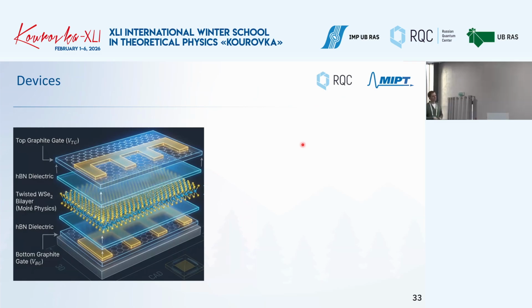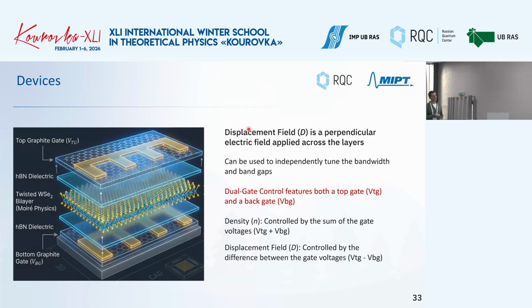While having this, you can change the so-called displacement field. It's the perpendicular electric field applied across the layers, so it can be used to independently tune the bandwidths and the gaps. This dual control allows you to change either the density of the carriers, when you change the sum of the gate voltages, top and bottom, or you can change the displacement field, which is controlled by the difference between top and back. So you can selectively change the filling factor and so on. It is very important, in order to easily follow what's going on in your structure, that you have these several gates in order to change the displacement field.